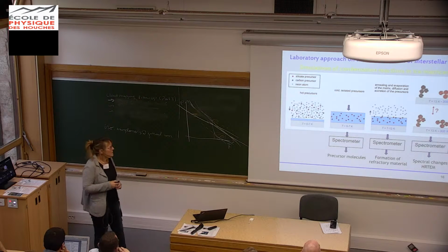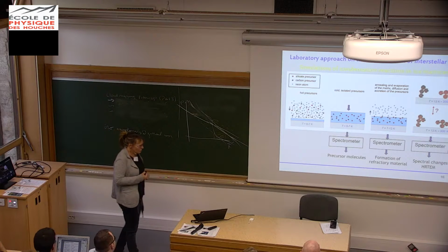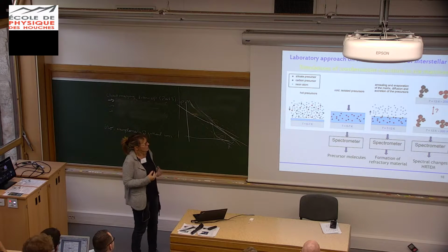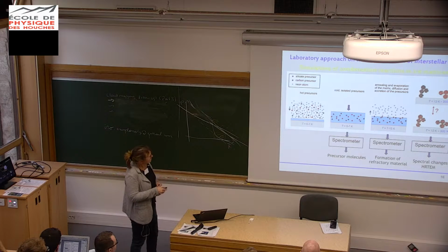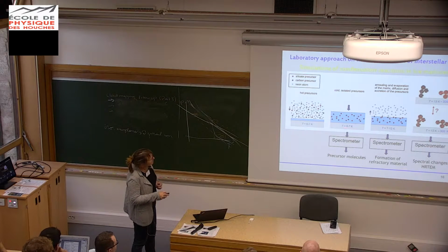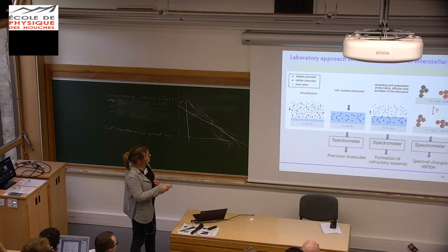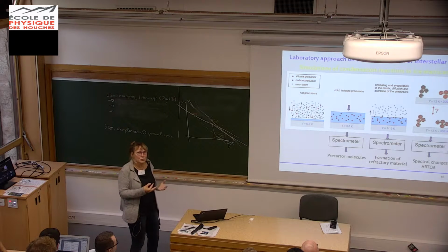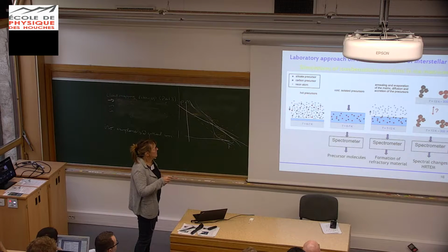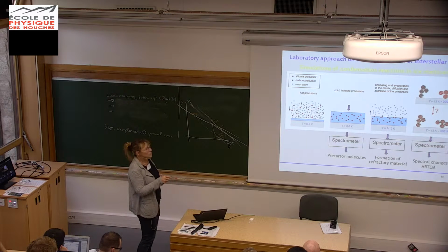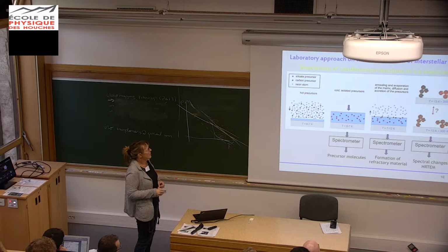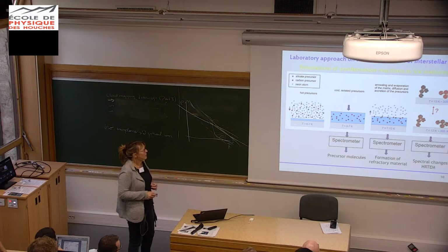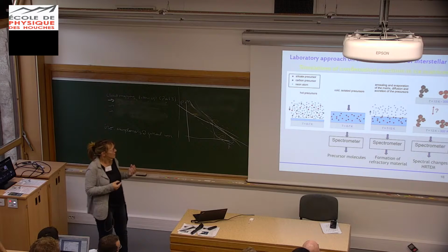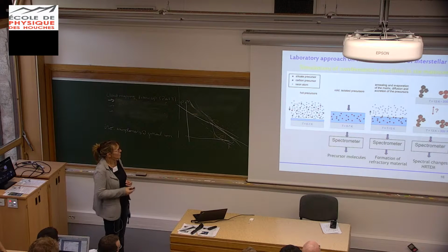We are really studying this process in the laboratory, and we simulate the conditions in a way which is shown here. We cool down a substrate to 6K, deposit precursors - silicate precursors, carbonaceous precursors we have produced by laser ablation. We deposit them on a cold substrate together with a rare gas ice matrix. We can do spectroscopy and identify the precursors here in this first step.